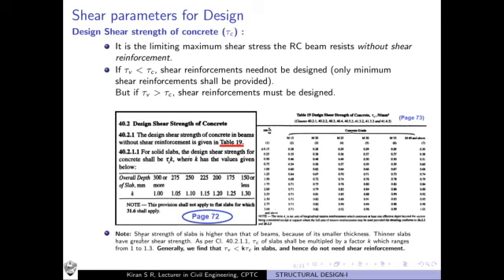Now for your understanding, please bear in mind that the shear strength of slab is greater than that of beams. Why? We know that a slab is a very thin member. It is very small in thickness. Because of its smaller thickness, when you subject it to loads, the development of shear stress is very low. It undergoes more bending than developing shear stress. That is exactly the reason why slabs develop less shear stress than bending stress, and because of which a factor K has been added as per clause 40.2.1.1. For solid slabs it is not just tau C, you have to multiply it with the value K, and the value of K is also given here.